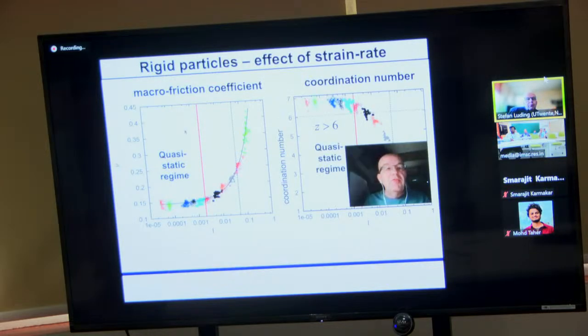Now, for rigid particles, there's an effective strain rate. I is the non-dimensional strain rate, I come back to that one, and the bulk friction follows the mu of I rheology for many different simulations. Different colors are different simulations with different global shear rates. The coordination number, the particle contact number, is also following a trend, but it's more complicated. There's this zigzag structure here, but they follow a trend also. I will not talk about coordination number today in detail.